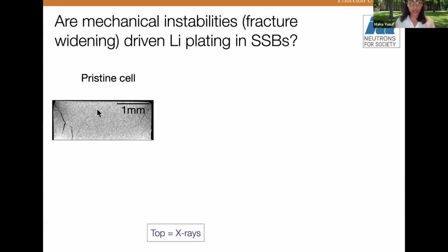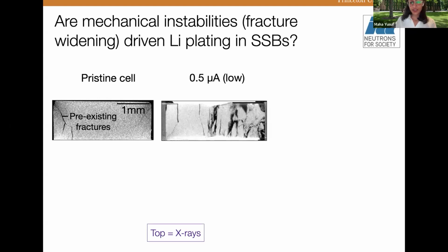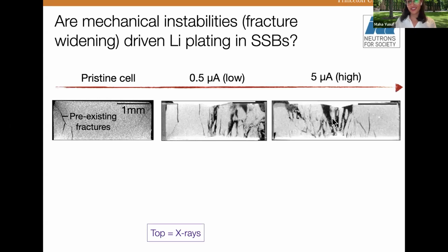So this is the X-ray reconstructed slice of a pristine cell, which means the cell was in the pristine state with no cycling. This image clearly shows that there are some existing fractures in this pellet. And if you look at the images of the two batteries that were charged at a low and high current density, we clearly see that there are some fractures which are widening, showing a potential correlation between fracture widening or mechanical instabilities and current density.